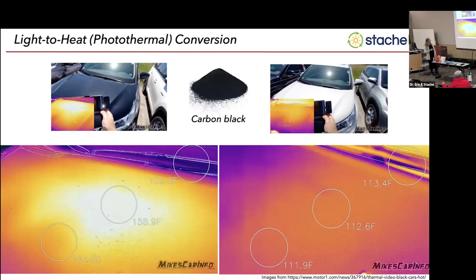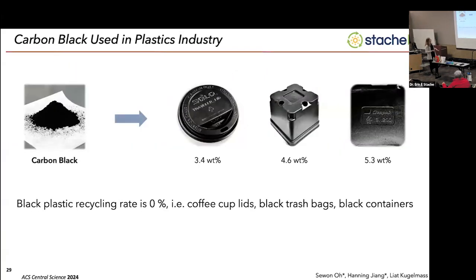And maybe we can take advantage of this to get rid of plastic that we already have. Whether the pigment is carbon black or something like that, that's what's being formulated into these plastics. That's what's giving them the black color. And it turns out if you shine light on this, it's going to get hot. If you shine enough light on it, you can actually cause it to depolymerize, do the pyrolysis mechanism, and convert into monomers. And so that's what we took advantage of.